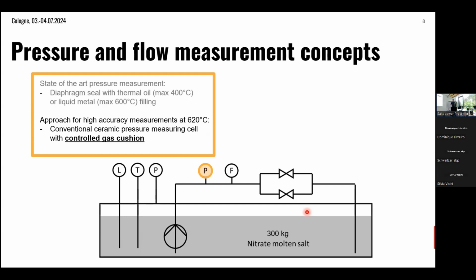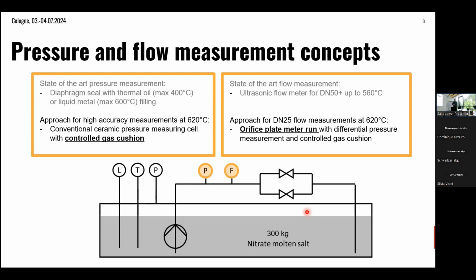And we use a slightly different approach, although we also have these Gaffron sensors installed. We rely on the high accuracy of conventional pressure sensors that are just shielded from the high temperature with a controlled gas cushion. That's our approach for the pressure measurements. For the flow measurements, usually at these high temperatures ultrasonic flow meters are suitable, but they are not available for our DN25 piping. So we used an orifice plate meter run with a differential pressure measurement, and also here we used a controlled gas cushion to shield from the high temperatures of 620 degrees.